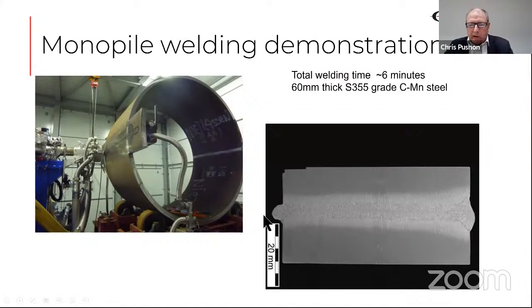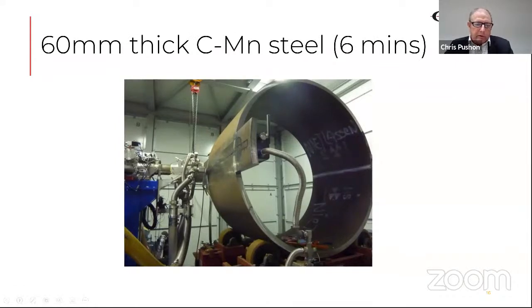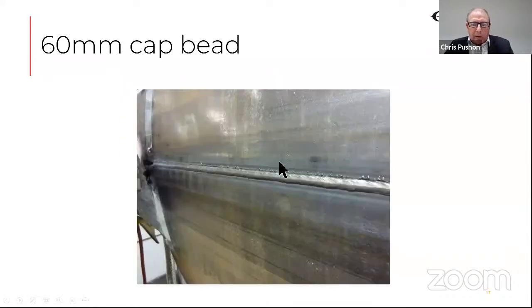What you see is the weld cap and roots, they're not ideal, but these can be readily dressed or ground flush if you need to. And this is the same picture. What you see is the weld cap is just a little bit spattery. And again, you might have to grind that to improve it. But over the years we've got better at it, and the weld beads are better.